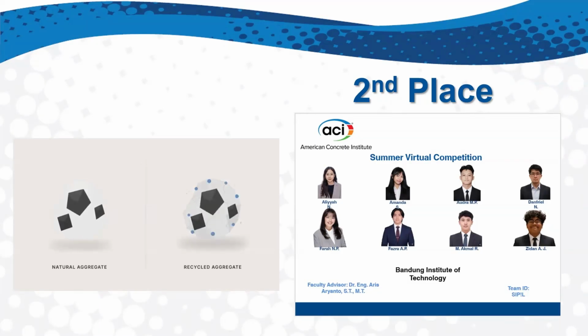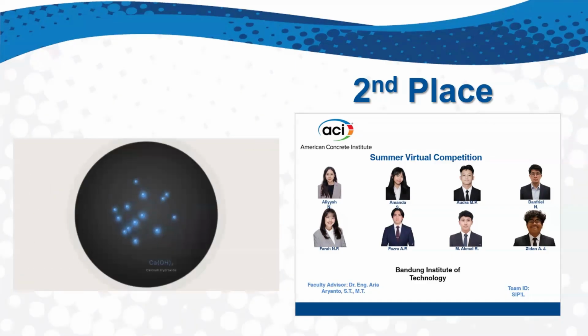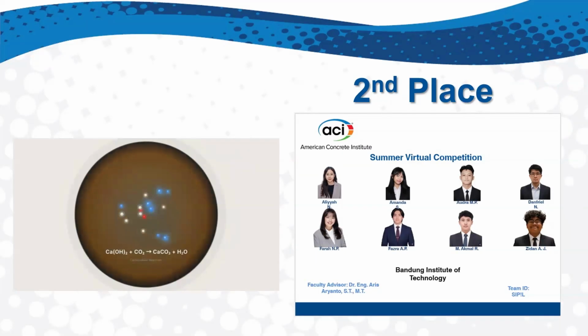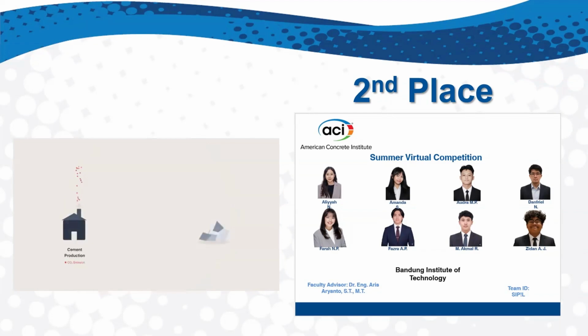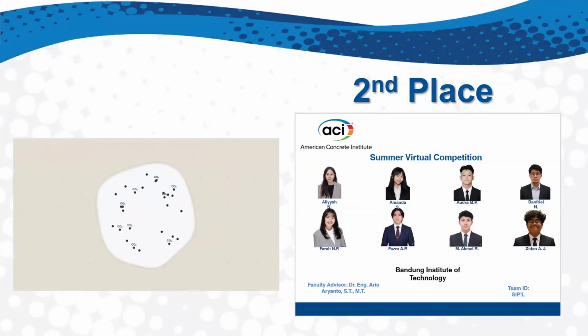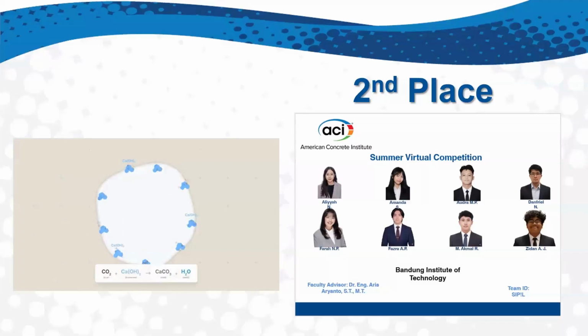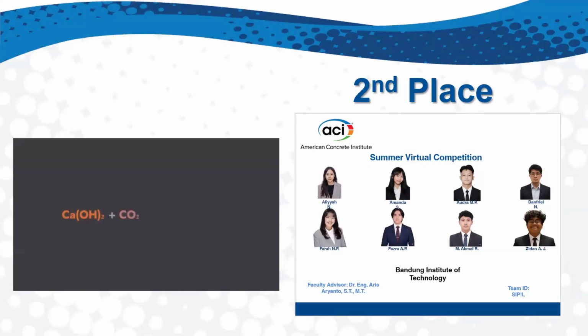The important part is this: that old mortar still contains calcium hydroxide, so the weakness also becomes the reaction site. This is where RCA and carbon capture combine. The carbon dioxide released earlier by the cement can be sent back into the recovered concrete. When carbon dioxide enters moist residual mortar, carbonation happens. Calcium hydroxide reacts with carbon dioxide to form calcium carbonate, also known as CaCO3, plus water.